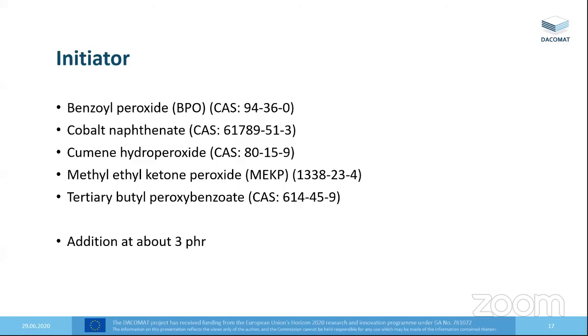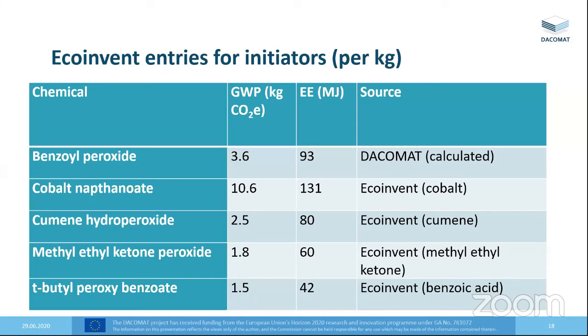So this is what we have. And if we look at some of those initiators, we find that actually we don't always have the entries that we want, but we might have something similar. So, for example, at the bottom, we have tertiary butyl peroxybenzoate, and in Eco-Invent, there is no tertiary butyl peroxybenzoate, but we do have benzoic acid. So as a first go at this, we select things which we think are reasonably close chemically, which involve similar process chains. I've actually chosen cobalt for cobalt naphthenate, because I know that the actual cobalt metal will have a much higher impact than the initiator itself.